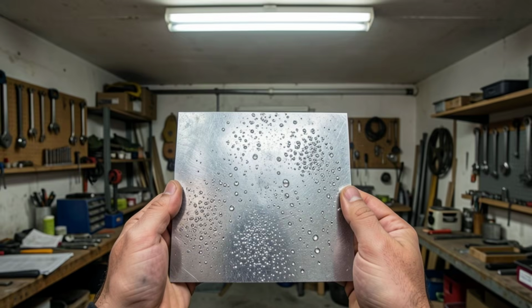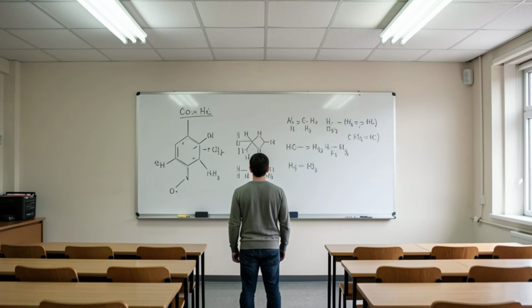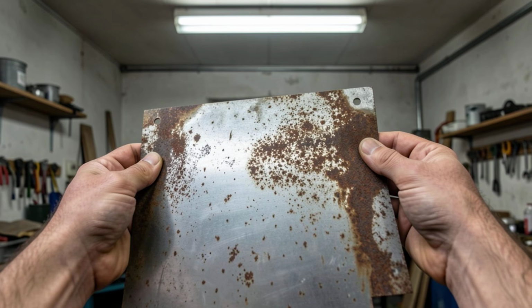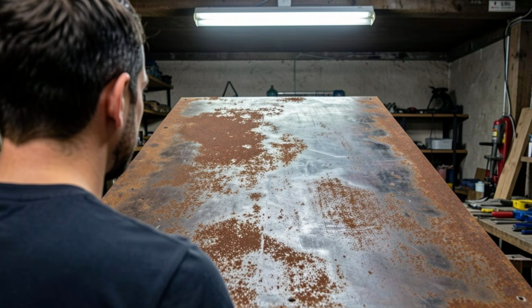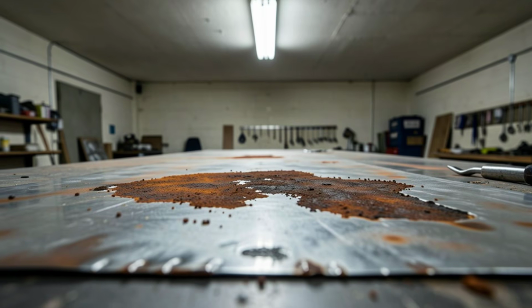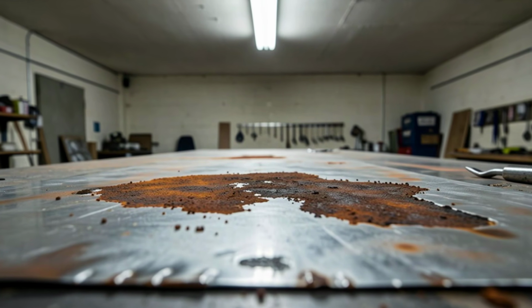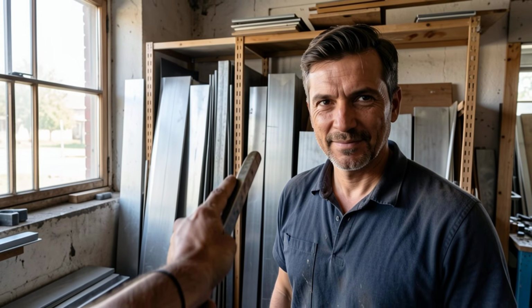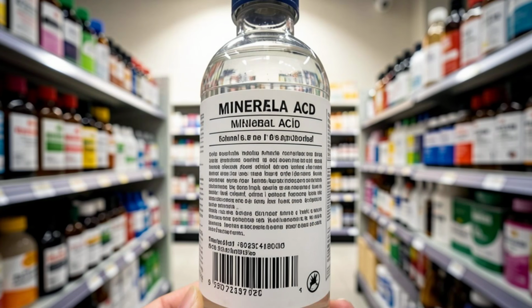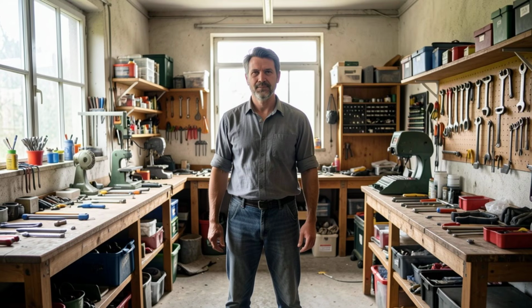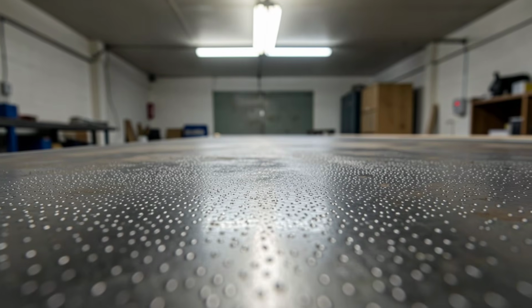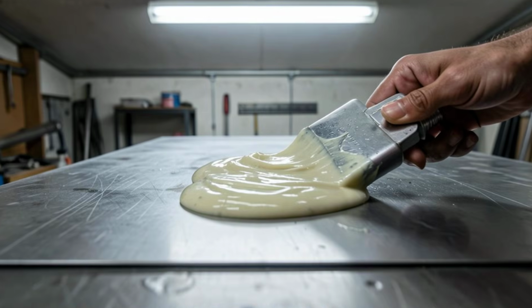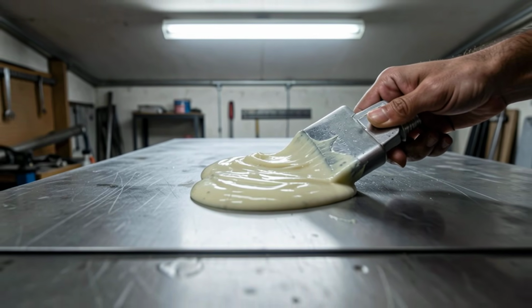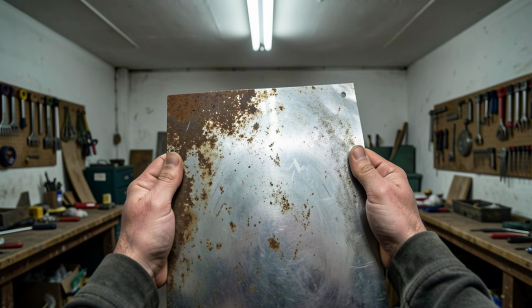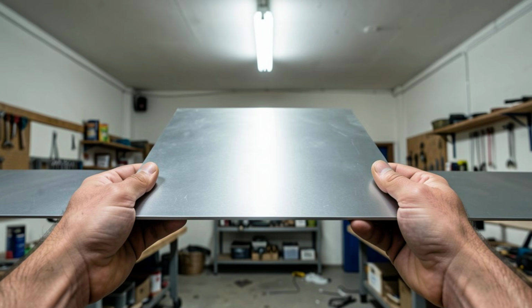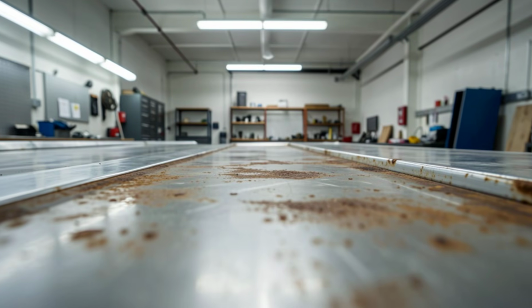These formulas are aggressive, and the reason they are aggressive is that they attack metal indiscriminately. They do not distinguish between the iron oxide that you want gone and the healthy base steel underneath it that you absolutely want to preserve. Mineral acid products dissolve rust, yes, but they also begin etching into the surface of the parent metal itself at the same time, which is why parts treated with heavy gel products frequently show micropitting and surface texture that was not there before, even after the rust is gone.